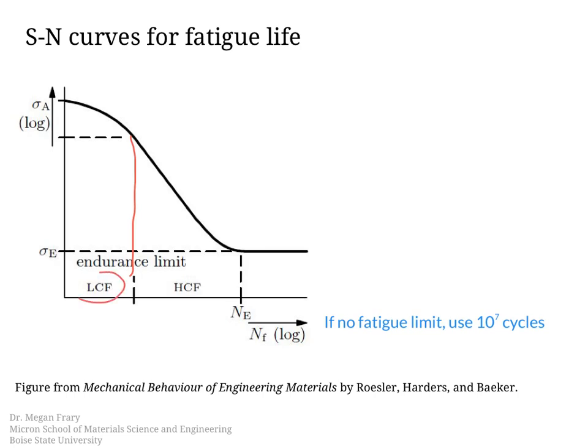And so this one that says LCF, that stands for low cycle fatigue. In the low cycle fatigue region, we notice that the slope here of the sigma A versus NF is somewhat lower. So that means that a small change in the stress amplitude results in a bigger change in the number of cycles to failure.